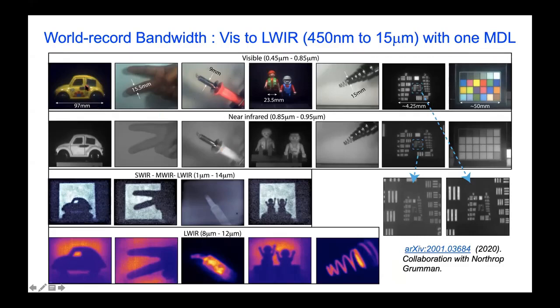Again, interestingly, in the near infrared image, for example, some of the details of this toy car disappear as expected, but you can see other details. And this is in the infrared. Now, these things are taken in different bands because we are actually using different filters in front of, in these two cases, silicon detectors, and in these two cases, various forms of microbolometer detectors. This bottom row is done with a FLIR camera. This is done with something called an electrophysics camera, which has a bigger spectral band. And you can get fairly nice performance, good resolution, and so on and so forth.